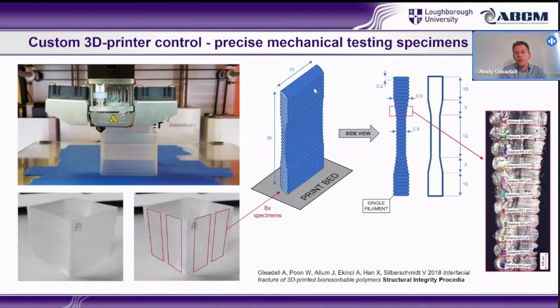for when you're doing those kind of tests, you really do need to think carefully about how to transition in such a way that your structure is always getting stronger, and that is not often just making it bigger, because when you make it bigger, you get changes in the lattice. So if you suddenly go from 5 unit cells to 6, you can get a critical change there where you get actually a poor area of contact between those 2 layers at the transition. So if you just take an ASTM specimen's overall shape and put it in sizing software, then it's not going to be easy to get it to fail consistently in the gauge section.